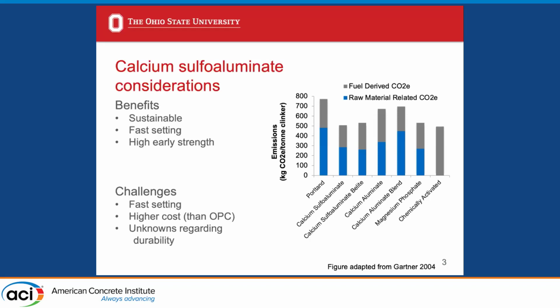And similarly, if you're placing a large amount of concrete on site, you'll need a way to delay that setting time. So we need to build out our resources for controlling these reactions and giving us enough working time to place the material. CSA cements also, because of their high alumina content, do have a higher cost than OPC. And so that can kind of prevent some users from wanting to use this sustainable material. And then finally, there's a large amount of unknowns regarding durability with CSA cements.